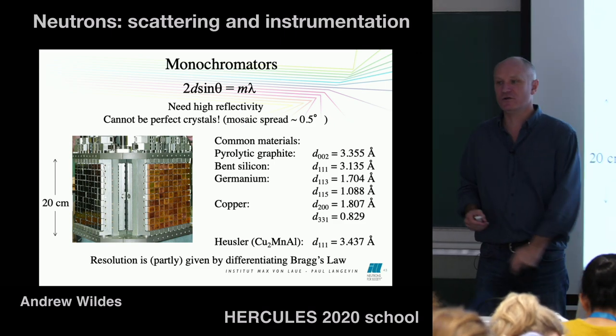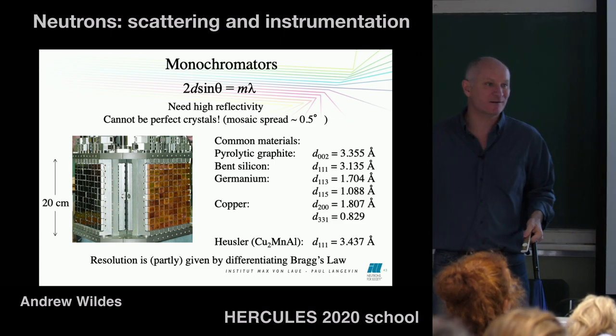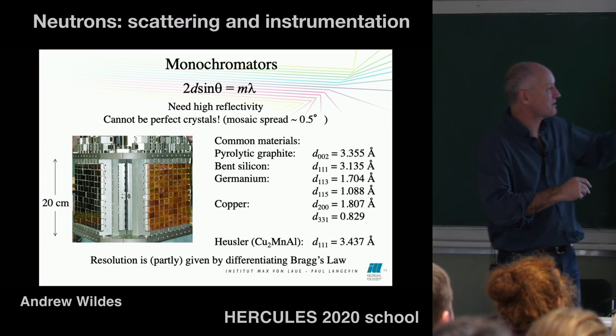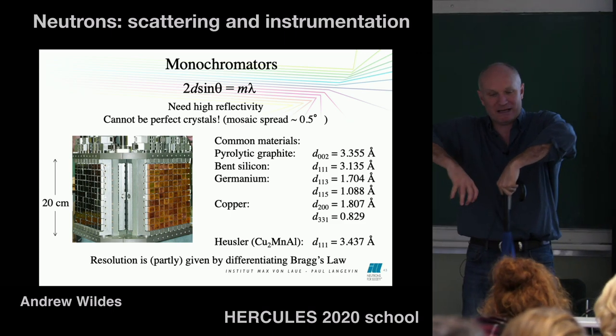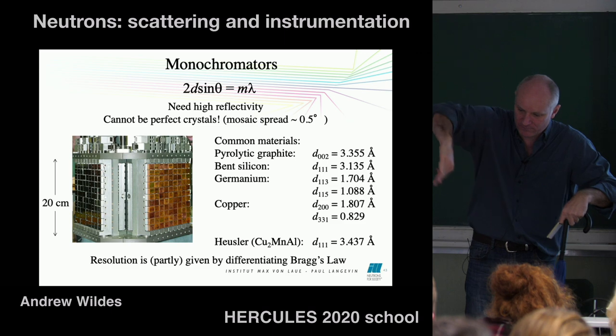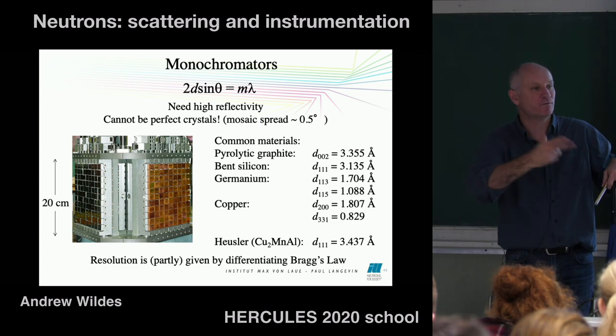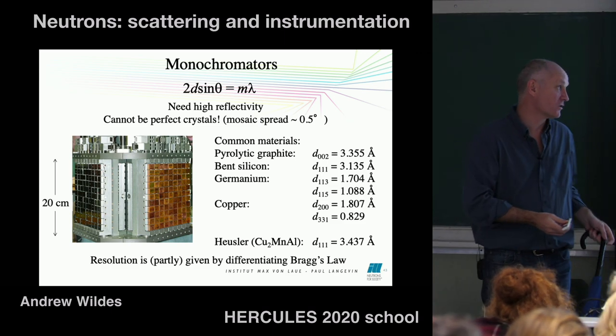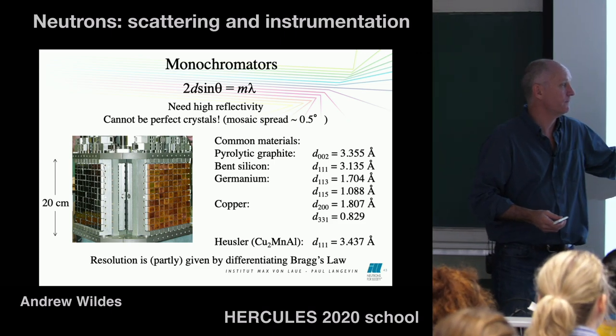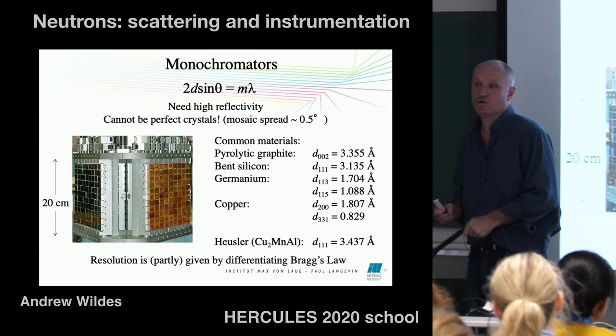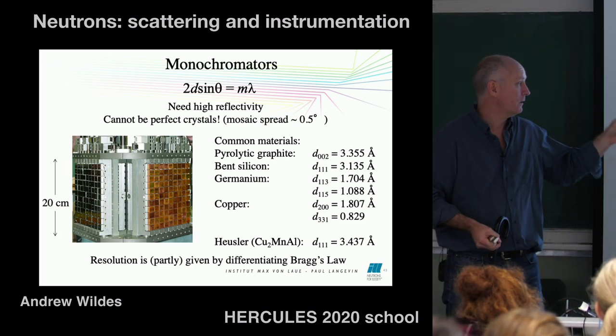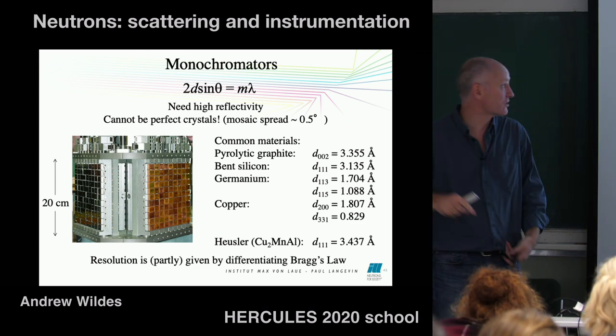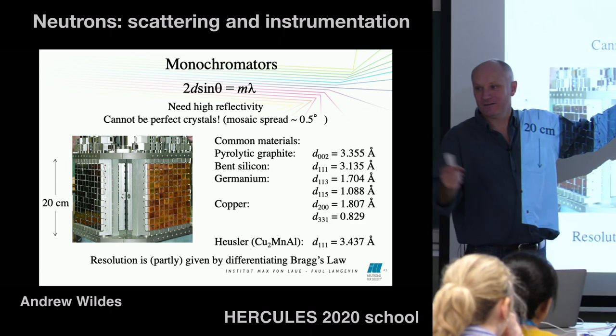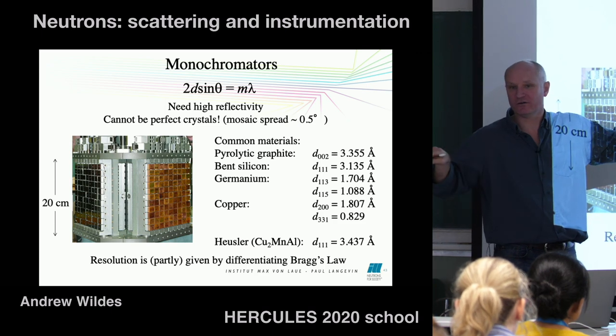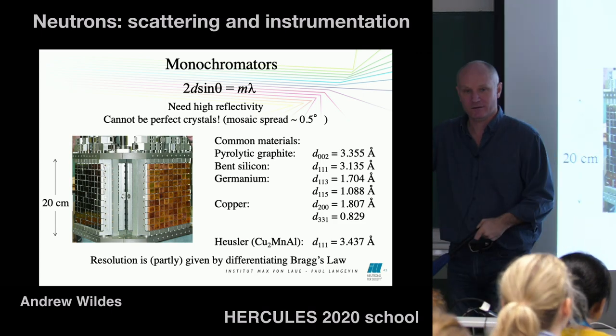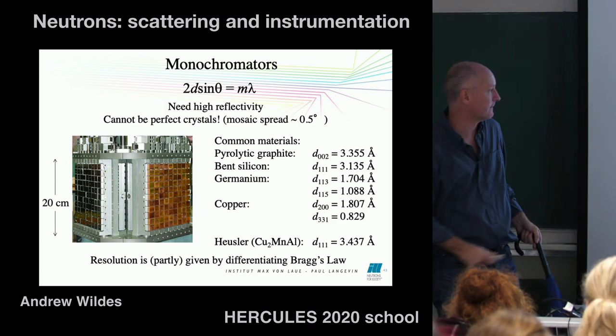Silicon we can use. That's very nice. It's perfect, so it's not good in that sense. But what you do is you literally bend it. You put it in a device that will physically bend it. And then you can get some sort of focusing effect from it as well. It also has an advantage because of the crystal structure that there is no 222 reflection out of silicon. So when you look at Bragg's law, n of 1 will reflect, n of 2 does not. And that's a property of the crystal structure factor.